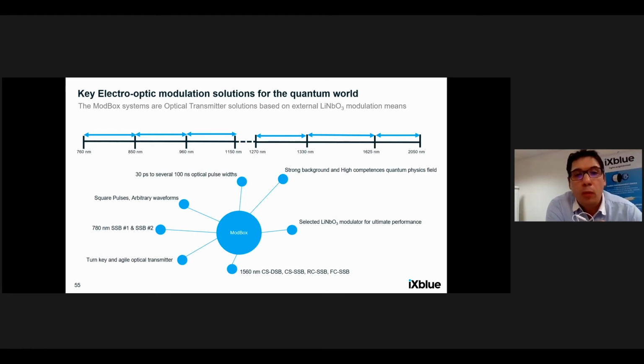For the laser pulse, we are capable to provide very short pulse from 30 picosecond to more than several hundred nanoseconds. This is a great performance, and this is due to our wet component. From these pulses, we can generate very square shape pulses, but also controllable waveform pulses by the use of arbitrary waveform generators. You have been also introduced a Mod Box we have co-developed with iXatom lab, and this solution is providing 2 sidebands at 780 nanometer, 500 milliwatt. As well, you have been introduced also some very flexible solution for single sideband generation at 1560 nanometer, carrier suppression, residual carrier suppression, and full carrier suppression.